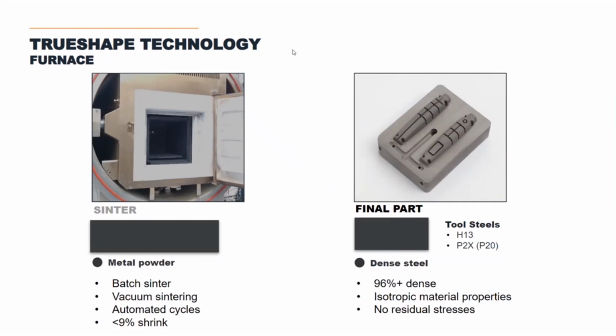After the printing is complete, we put the part into a furnace. If you're familiar with other sinter technologies like metal injection molding or press and sinter technologies, it's similar in that we're putting this metal powder and binder combination into a furnace. This first removes any binder that was left in the part, and the part densifies and shrinks. Shrinks about less than 9% in this process.